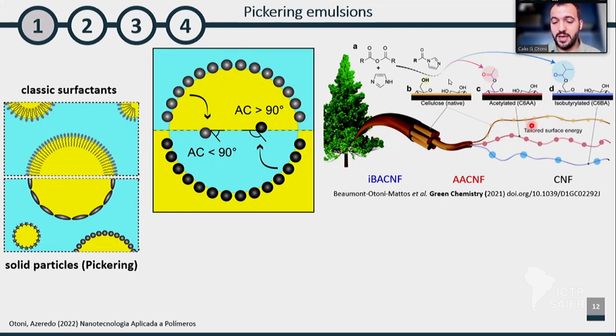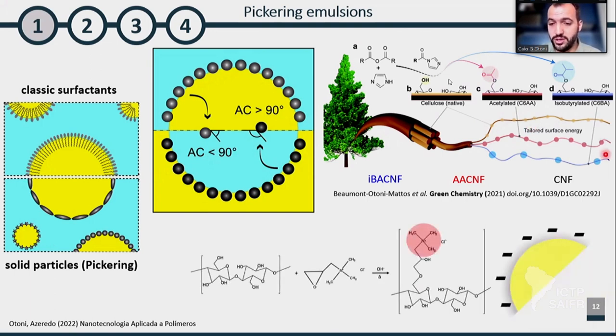But there is another possibility without playing with these, because there are drawbacks, there are side effects. There is the option of introducing surface charge. As I told you, these hydroxyls are functional groups eager to react. So for instance, in this case, we have an epoxide ring. There is a nucleophilic attack onto these hydroxyls, and we can covalently graft a quaternary ammonium group that is positively charged at all pH that are reasonable for us. And in an emulsion, it's likely that the droplets are negatively charged. So we have a cationic species and an anionic interface because of free fatty acids and different stuff.